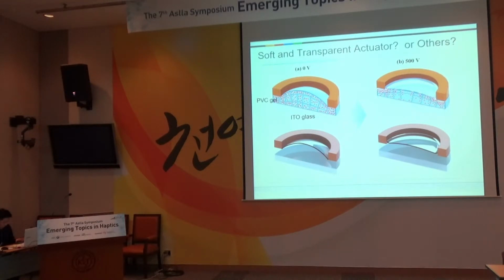At the time, Q suggested to me, how about making a lens? Wow, that is a great idea. So we made a lens. We prepared the glass, and then we put the PVC gel on the glass and pushed the PVC gel with a circular-shaped electrode. When we provide voltage, the dipole moves to the anode, and the middle part goes down. So according to the voltage, we can change the focal length.